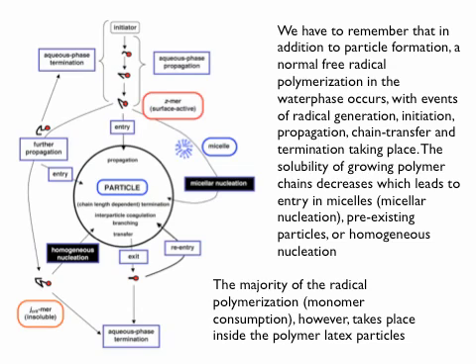Suddenly I'm classed as a particle. Once I am a particle, I can grow. From my initiator I can become a z-mer and enter an already existing particle — which is interesting because that particle could already contain a radical. So if I am another radical, could there be two radicals in the same particle? The particle is pretty small, so let's look at that in a bit more detail later.